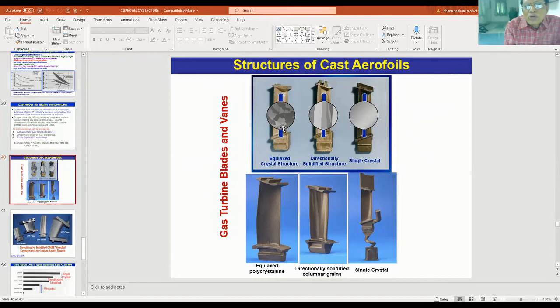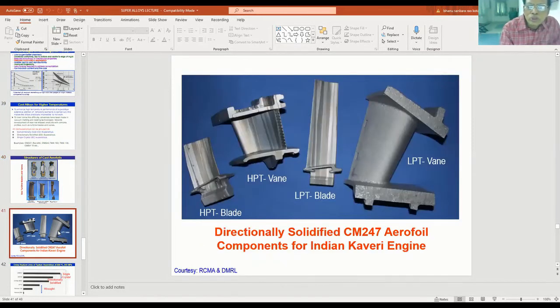Transverse grain boundaries are not required because they produce creep cavities at elevated temperatures. Therefore, we have to eliminate the transverse grain boundaries and produce grains like this in the form of directional solidification, and then grains are produced like this. Nowadays, the grain boundaries are completely eliminated and single crystal superalloys are produced for the turbine blades, for gas turbine blades. You can see those products for the Kaveri engine, which have been produced at DMRL, Hyderabad. These are directionally solidified. You see the grains are oriented in this direction.